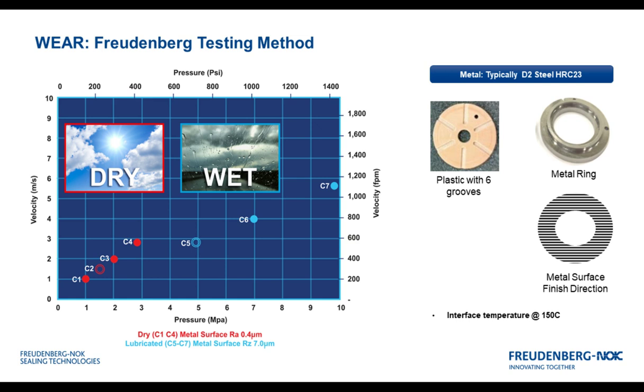One of the key benefits we need to do to use these materials and get the benefit from them is to understand the effects of wear. Freudenberg has developed their own wear standard for doing so. The main reason for doing this is to eliminate noise and variation when we add fillers to the systems to really understand the key failure modes of these systems. That way we can know what the impact is of a filler and how that will affect the failures. There are two key testing conditions that we want to look at, of course, is dry. What do we have when we do not have lubrication, and then lubricated or wet wear.